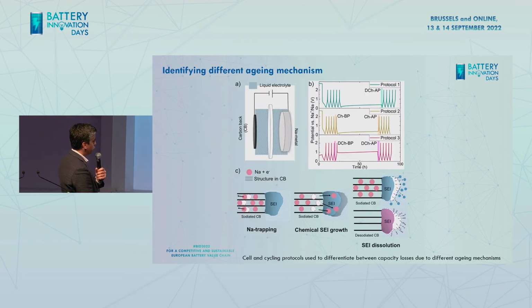So from there, we tried to continue a bit more to understand what's happening. If you look at the schematic picture in the bottom, on the right, you can see a schematic of this SEI dissolution. So you have the SEI, it can be dissolved into the liquid electrolyte. That's what you see on the right. And the electrode can be sodiated or dissodiated. In the middle, you can see that we also try to understand chemical growth of SEI. So that can happen with no external current or potential. So if there is any leakage through this SEI, the sodium ions can be leaked out from the SEI to react, and then the SEI thickness will grow.